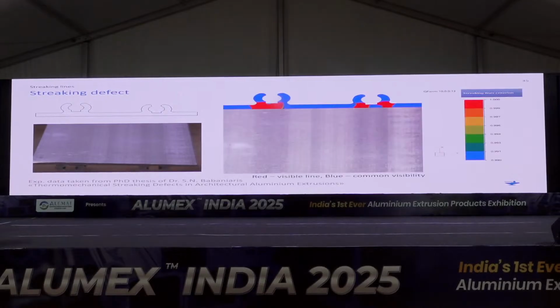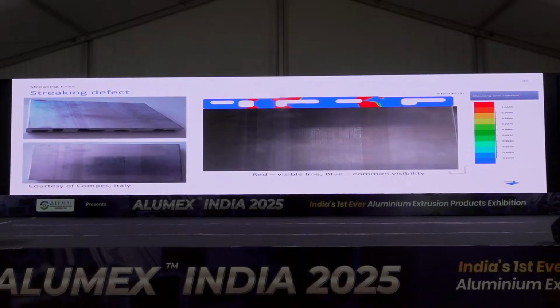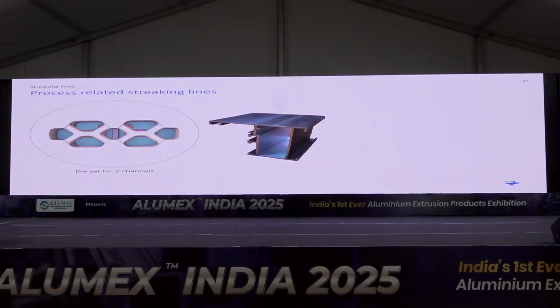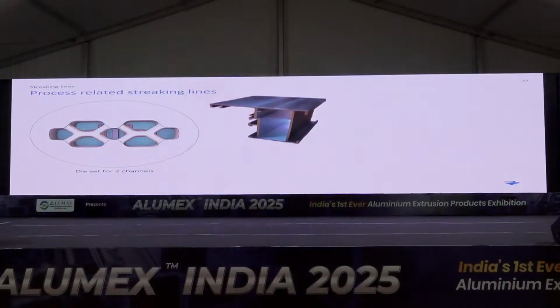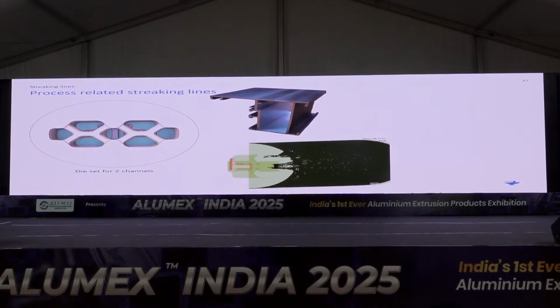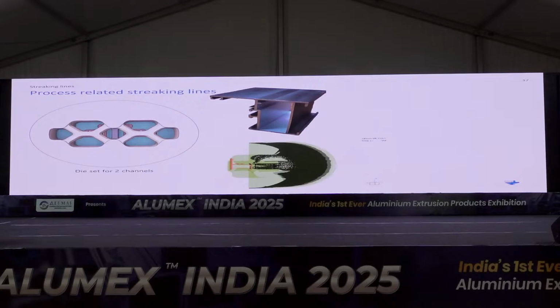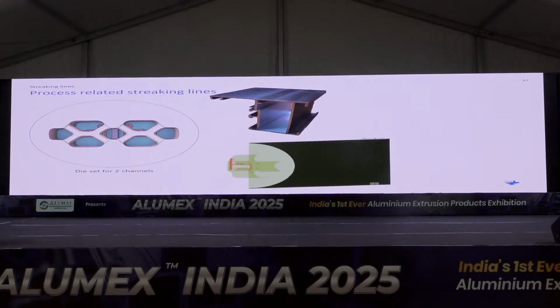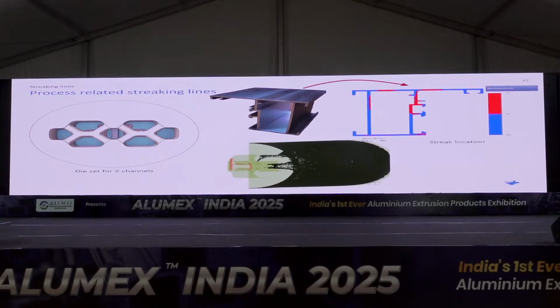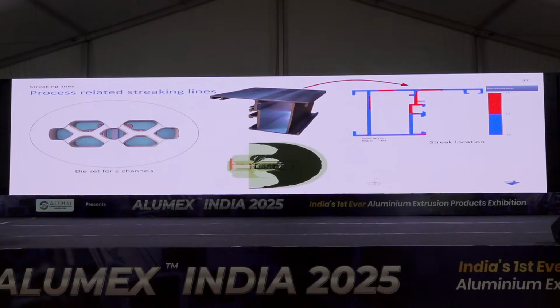Typical areas are the T-section or areas where we have screw ports, so there is some variation of the section itself. Here you can see with the different screw bosses and thickness nearby them, a different formation of the streaks: one big and two smaller streaks near screw bosses. Another example, another case. Like in the previous case, the reason it looks so is the billet skin. This is a two-cavity design, and here you can see that during the extrusion, in the central port, a lot of contaminated, oxidized areas of the billet start to flow, which is the reason, or could be one of the reasons, that led to this defect.